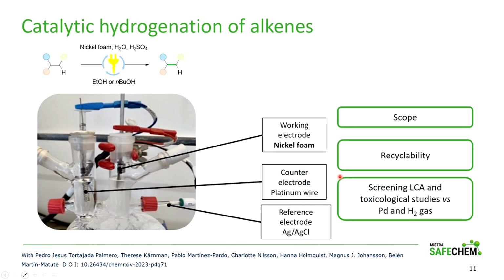So this is the setup that we used, the electrochemical setup, where we have here the working electrode, that for us is the nickel foam, and we have a counter electrode, which is a platinum wire, and then we of course need a reference electrode. And we optimized the reaction, studied the scope, as I will show just in a minute. Important for us is to show that the metals used are recyclable.